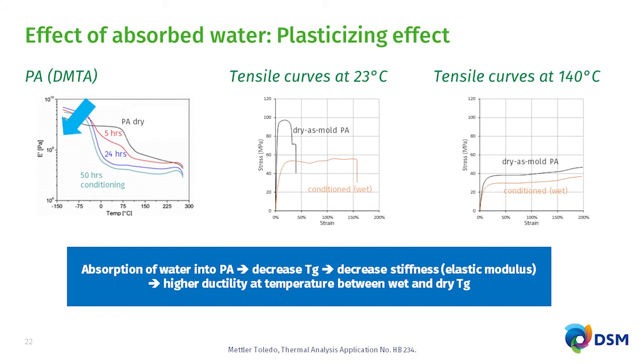Now, what is the consequence of having this low Tg? In principle, when you do a tensile test at room temperature on dry polyamide, as indicated in the middle figure by the black curve, you measure the property of the polymer below its Tg. But as soon as the polyamide absorbs water and the Tg goes below room temperature, what you measure is the property of polyamide above its Tg. So usually what you find is lower tensile strength and a much more ductile material, as you see in the orange curve.